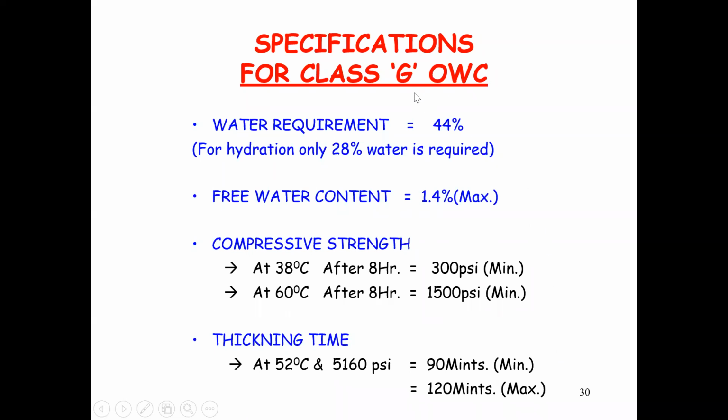There are many other parameters like high sulfate resistance, I told you, C3A compositions. Actually, there are four main compositions of this cement. I have not gone into those details, as those are the chemistry part of this. There is tricalcium aluminate, which is minimum 3%. Then tetracalcium aluminoferrite,